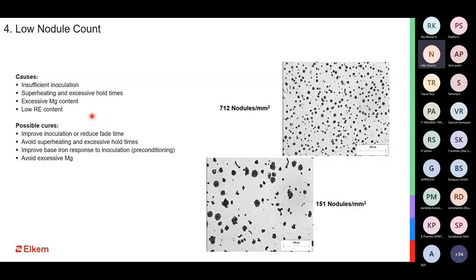Because if you look at the micro level inside the metal, there are so many turbulent and dynamic actions happening. There is metal all around this nodule which is trying to push it, you know, deform it or change its shape. And smaller the nodule, more easy it is for it to hold its shape. As it keeps growing bigger, which happens in case of poor nodule count, it tries to deform and change its shape. So in many cases, the problem of poor nodularity can also be solved by increasing the nodule count.